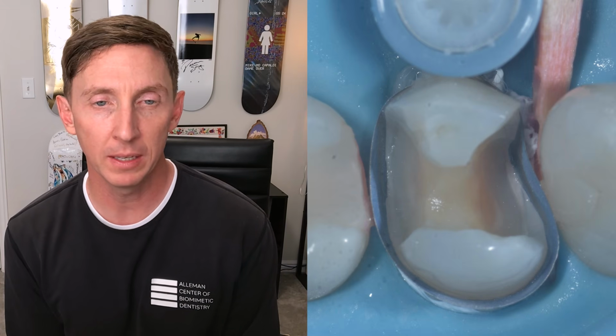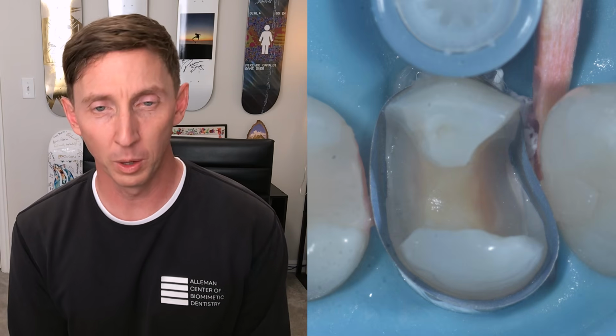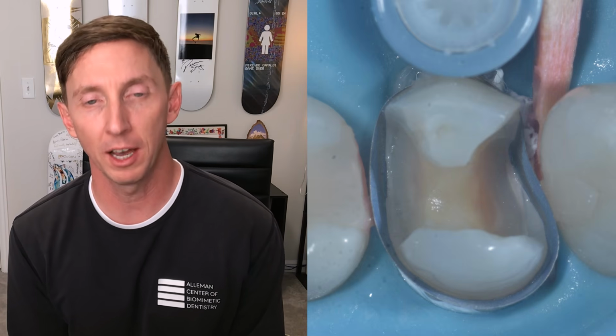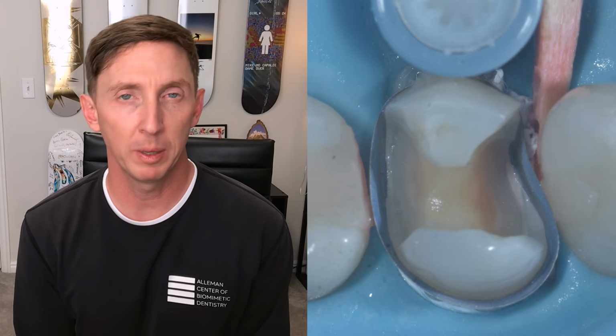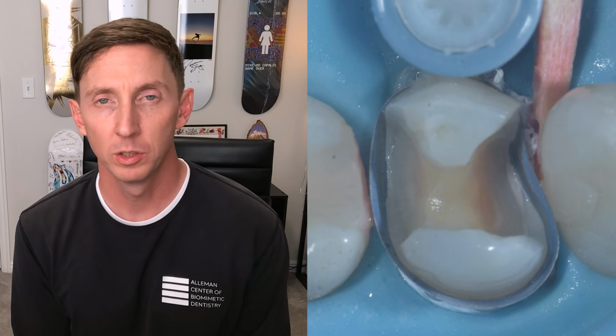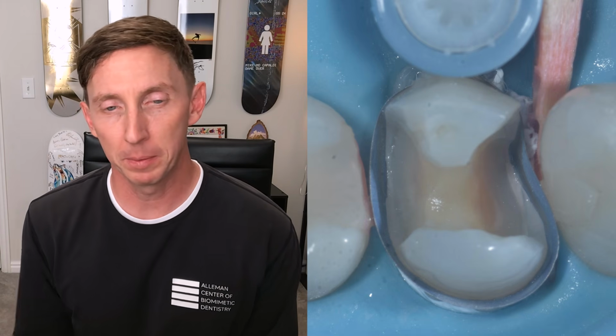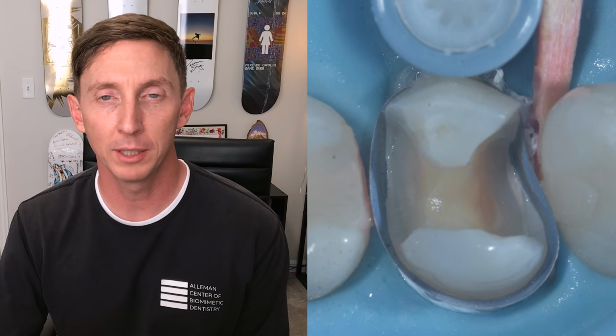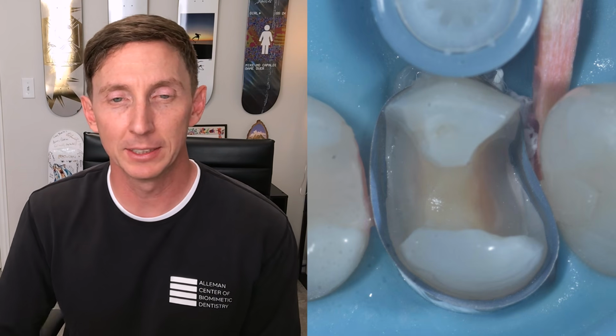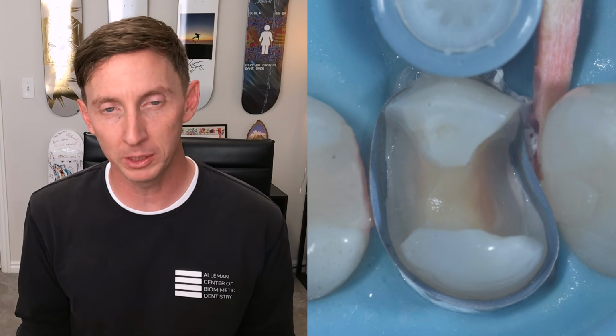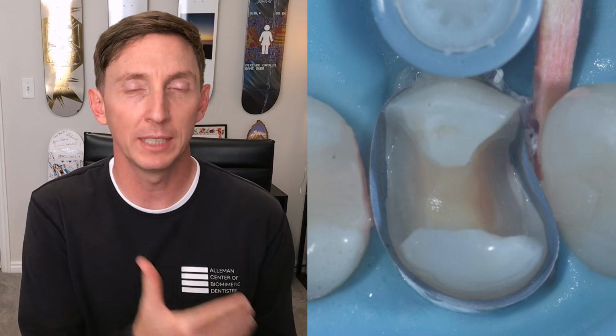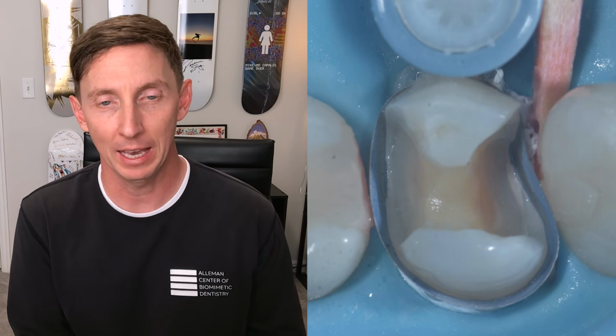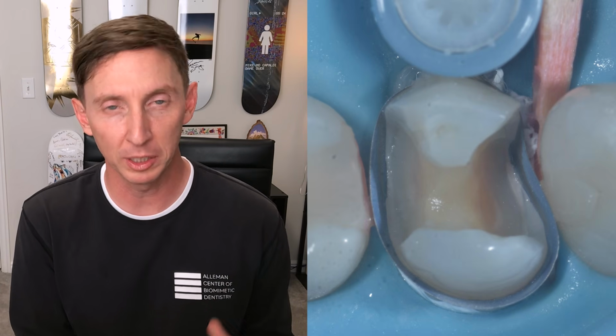Now, as you're priming with a mild self-etch adhesive, there's an intense chemical interaction between the molecule MDP and hydroxyapatite, where we have a superficial dissolution of the hydroxyapatite that is caused by the MDP molecule. So the way they described it in this paper by Fukugawa in 2006 is that there's an MDP adsorption, and then there's a subsequent deposition of the MDP calcium salt, and it's extremely stable.